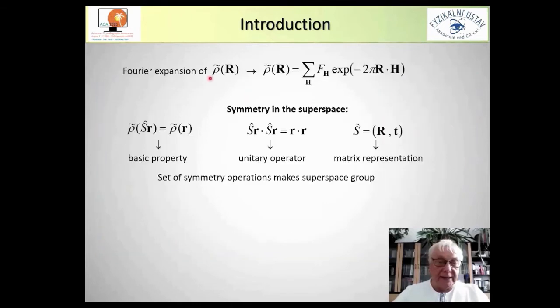Because the generalized electron density has translational symmetry in superspace, we can make an expansion of this density into Fourier coefficients. These Fourier coefficients, the structure factors, are related to measured intensities of main and satellite reflections. The only difference with respect to three-dimensional structures is that this structure factor is now a function of 3+d indices.